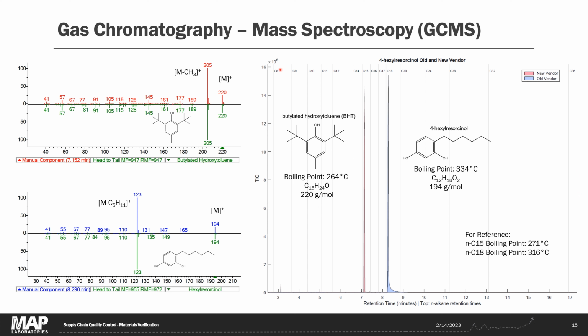I have the elution times of the normal alkanes up here for reference, and we can see that those boiling points roughly match. The reason that BHT has a lower boiling point, even though it's a larger molecule, is because of the lack of hydrogen bonding. That hydrogen bonding helps the molecules stick together and increases the phase change temperature.